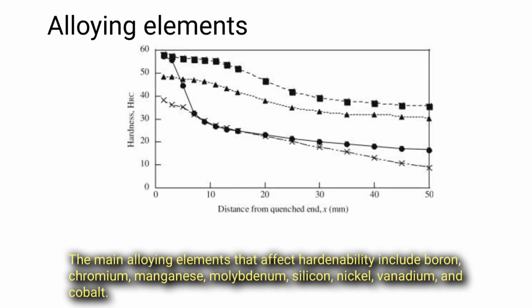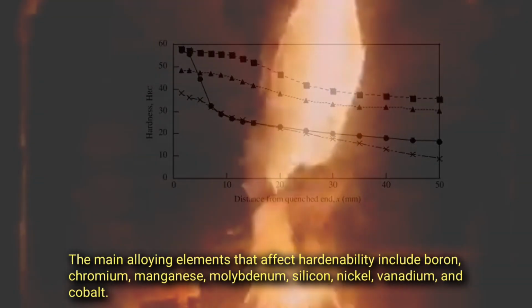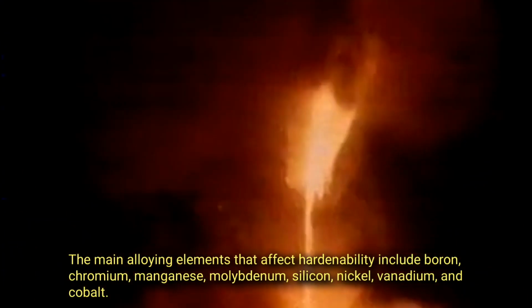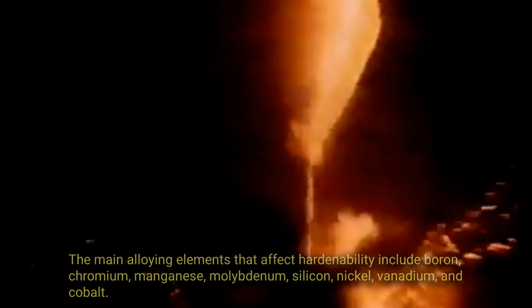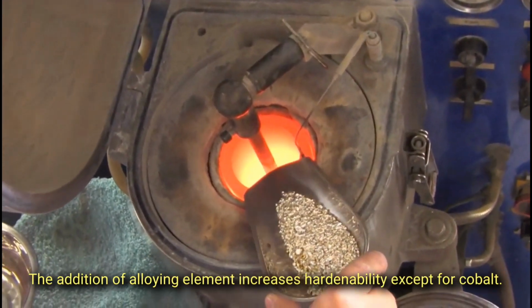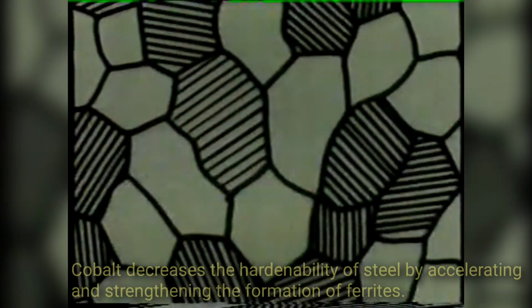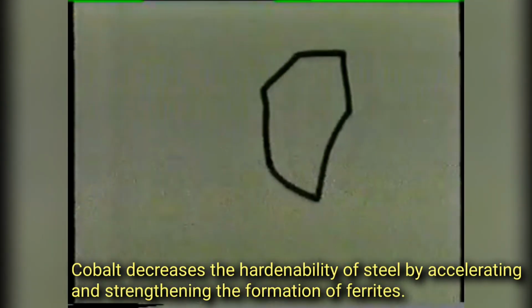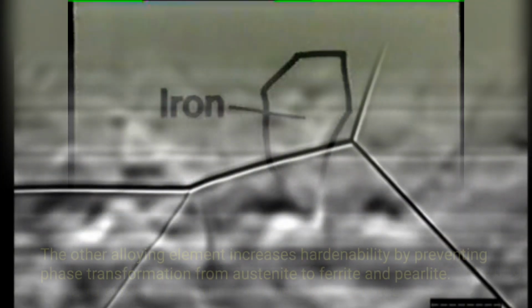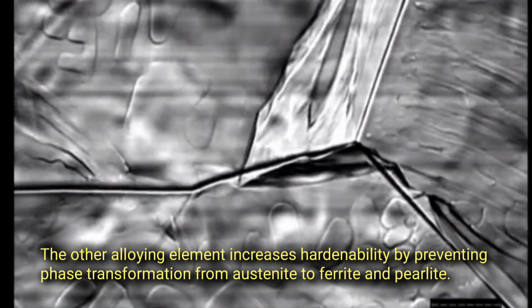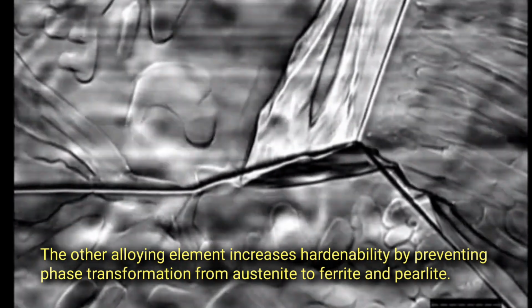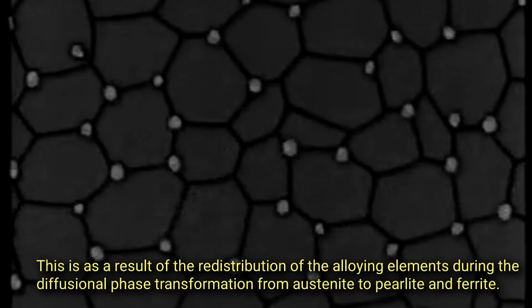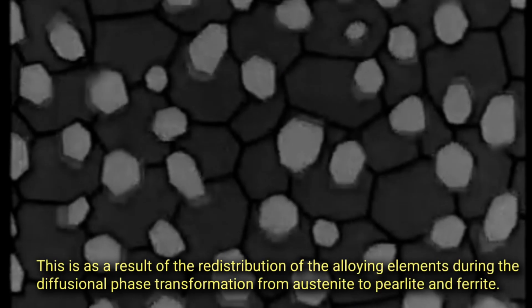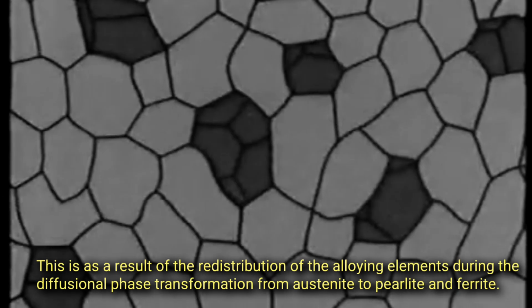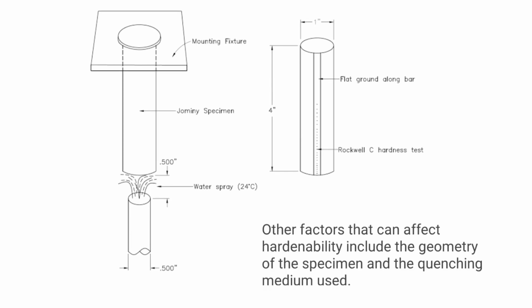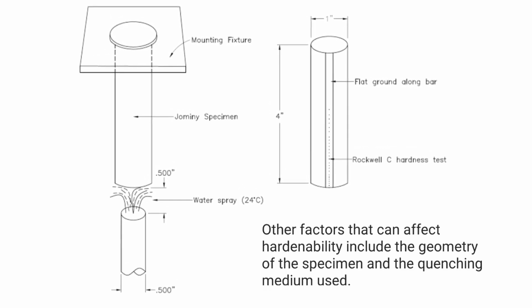Alloying elements. The main alloying elements that affect hardenability include boron, chromium, manganese, molybdenum, silicon, nickel, vanadium, and cobalt. The addition of alloying elements increases hardenability except for cobalt. Cobalt decreases the hardenability of steel by accelerating and strengthening the formation of ferrite. The other alloying elements increase hardenability by preventing phase transformation from austenite to ferrite and pearlite. This is a result of the redistribution of the alloying elements during the diffusion phase transformation from austenite to pearlite and ferrite.